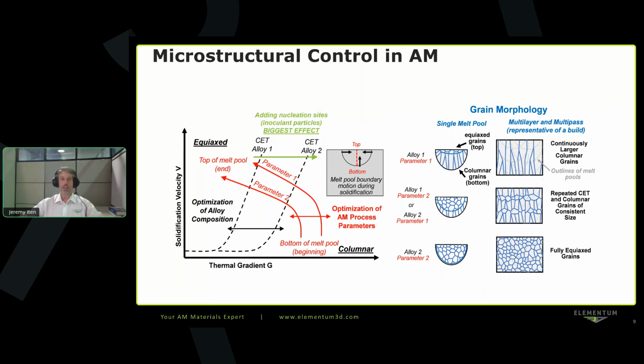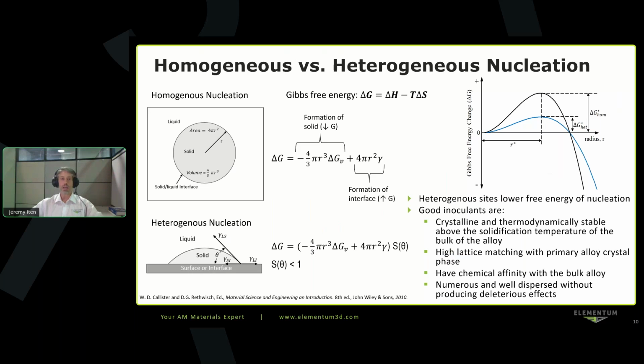So there's another method, and that is introducing heterogeneous nucleation sites, and that's what I'm going to focus on talking the most about here. So in solidification, you have homogeneous solidification, and you also have heterogeneous solidification that can take place, or heterogeneous nucleation that can take place. And heterogeneous nucleation is where you're solidifying your bulk material onto a secondary structure. It could be the side of a container wall if you're doing a casting. You can initiate your solidification from the container wall. But if you can provide a dispersion of very small seeds within your liquid melt pool, you can also solidify off of those seeds. And that can help you to get a very fine equiax microstructure.